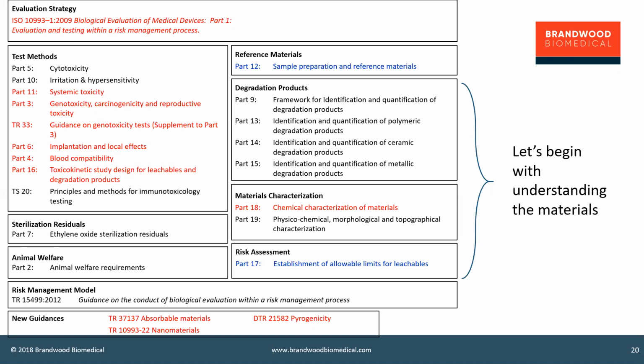And then part 17 provides a framework for risk assessment where you can quantify what might come out of a device in terms of leachable substances, residues that can be dissolved out of the device and end up in the tissues. And if you can characterize those, identify what's present by doing extractions and analytical chemistry, then you can make some reasonable judgments about whether there is a hazard that arises from the substances that may come out of the device. And for 3D printed metal devices, there shouldn't be anything coming out at all, or very little.